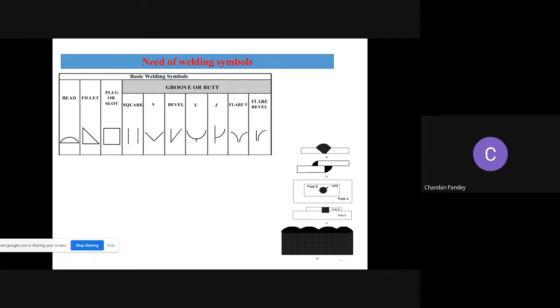So if you are going to deposit a layer over the surface of your workpiece, that is called bead on plate, and generally that is represented by the first symbol, the bead on plate, just a deposited layer over the surface of the workpiece to enhance the mechanical property. And during the joint design, the important thing that we consider is the welding parameters and the weld bead geometry. If you want to optimize the welding process parameters on the basis of weld bead geometry, suppose this one is the plate, and for different welding parameters, we deposit a layer over the surface of the workpiece, and after that we cut a cross section of it, and after grinding, etching and polishing, we check the depth of penetration and bead width.